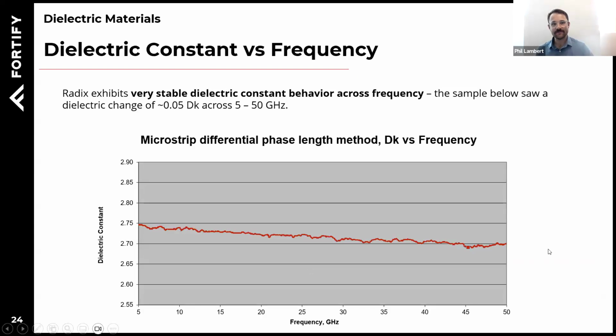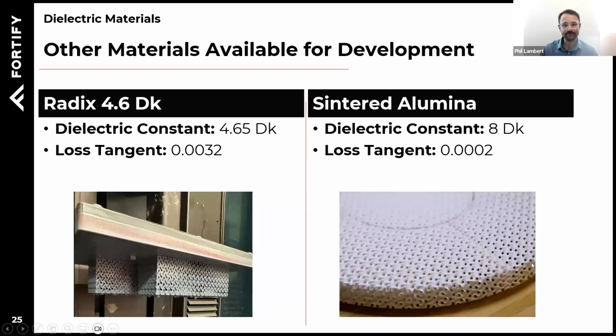And when you look at this material's behavior across frequency, it's very stable. We've characterized this using microstrip differential phase method. And you can see from 5 gigahertz up to 50 gigahertz, very, very little change in the dielectric constant across frequency. So you can have a lot of confidence in this material being very stable when you're doing wideband lensing.